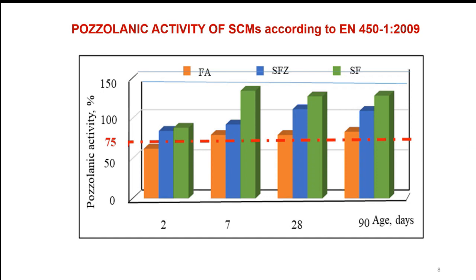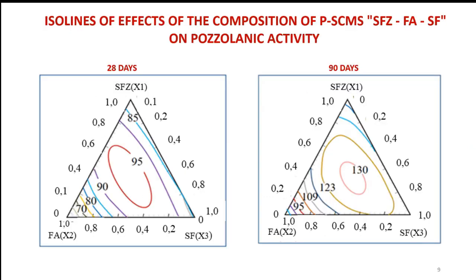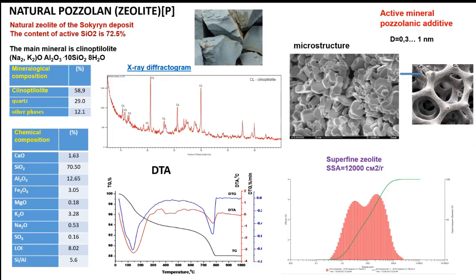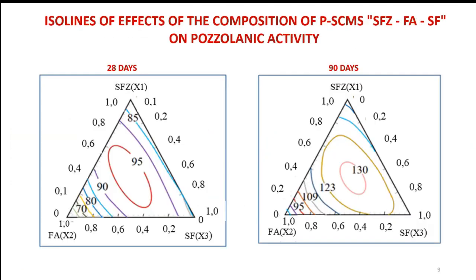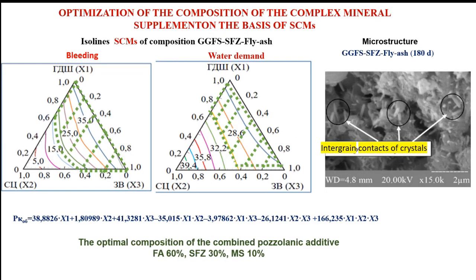Highly dispersed supplementary cementitious materials such as superfine zeolite and microsilica are characterized by increased water demand and have low bleeding. Fly ash has lower dispersion compared to the other pozzolanic materials. Fly ash is characterized by particles of the correct spherical shape, which provide a plasticizing effect due to the roller-bearing effect. Therefore, its water demand is reduced by 27%, but it is characterized by significant bleeding.